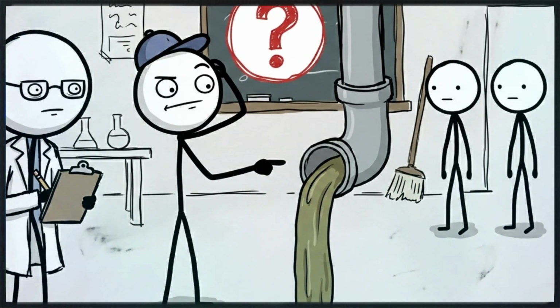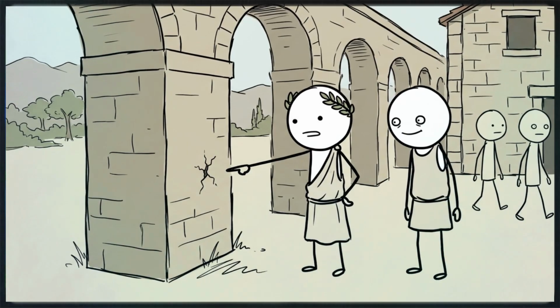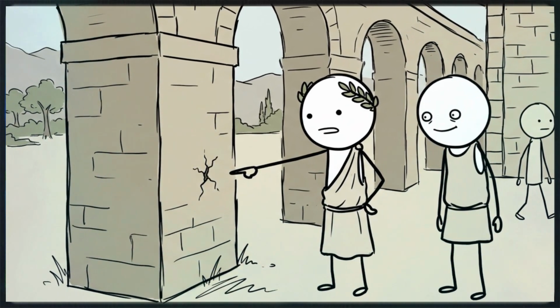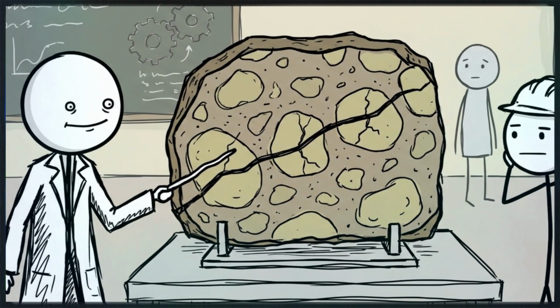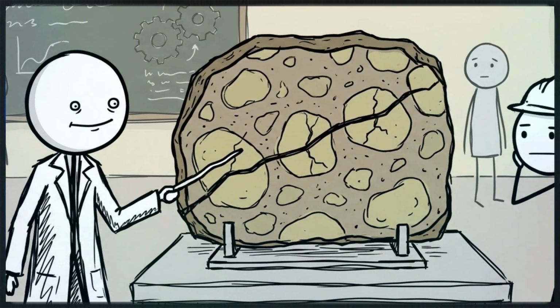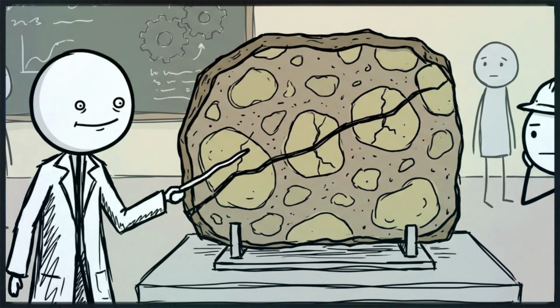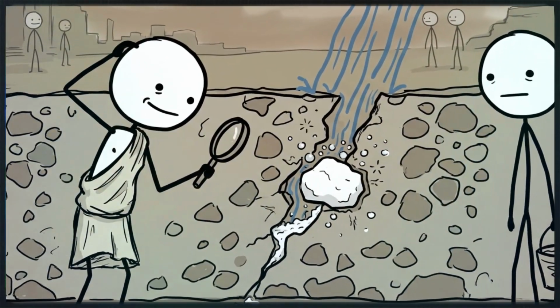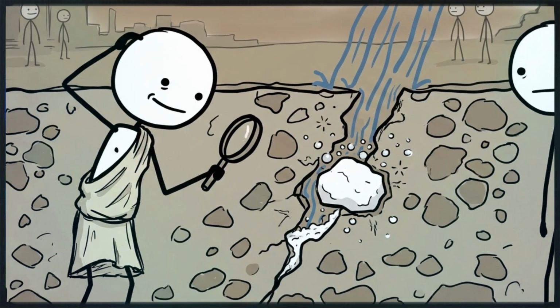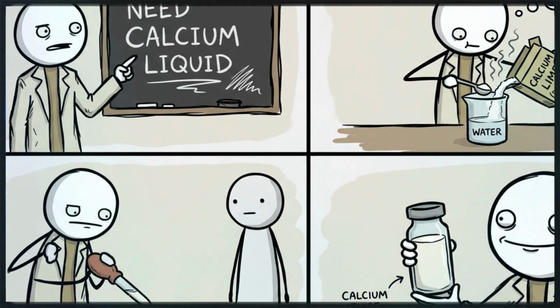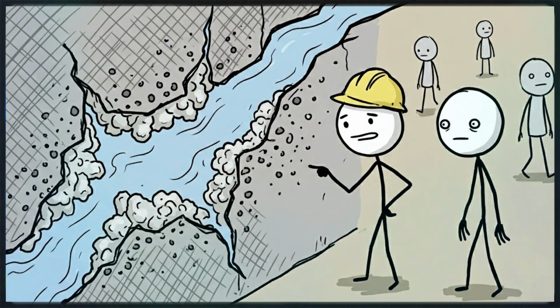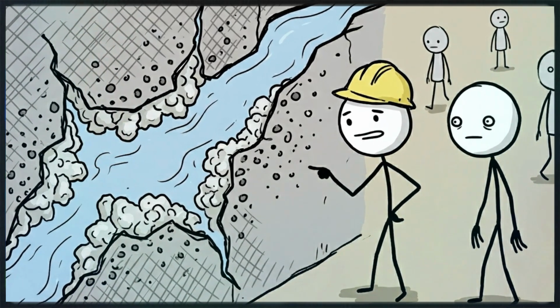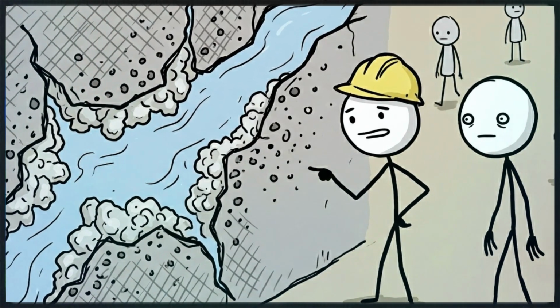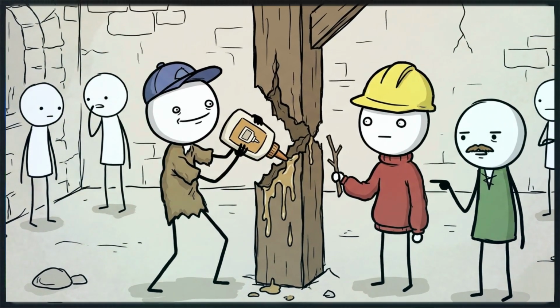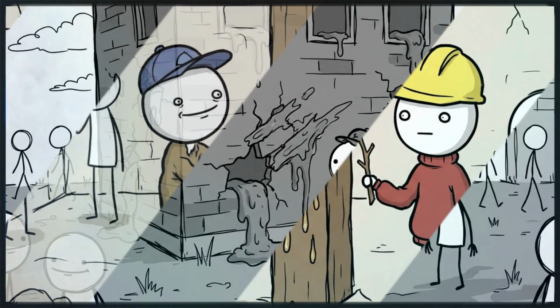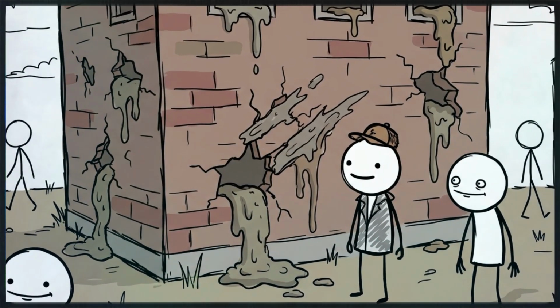The fluid dynamics of this self-healing process are astonishing. When tectonic stress or physical settling causes a microcrack to form in a Roman structure, the fracture naturally travels through the lime clasts as they have a higher surface area and are slightly more brittle than the surrounding matrix. When seawater or rain inevitably breaches the crack, it strikes the exposed lime clast. This creates a highly localized, calcium-saturated alkaline fluid. As this fluid spreads through the microcrack, it rapidly reacts with the surrounding pozzolanic ash and recrystallizes into calcium carbonate, effectively gluing the fracture shut before it can structurally propagate. The building autonomously bleeds a mineral sealant to stitch its own wounds.